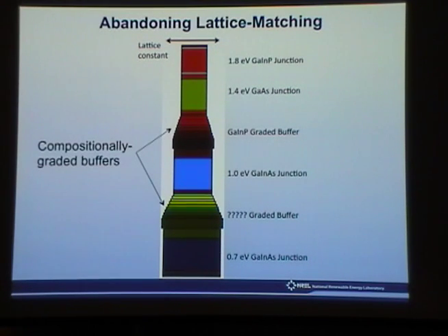But what you try to do is engineer it so that all of the dislocations lie in the interface between each layer. And so by the time you get to this layer, you have a relaxed structure that is dislocation-free. Okay, so two things. It's relaxed, and all the dislocations that had to be created in order to mediate the change in lattice constant from here to here hopefully lie within these interfaces and don't turn themselves into that material.